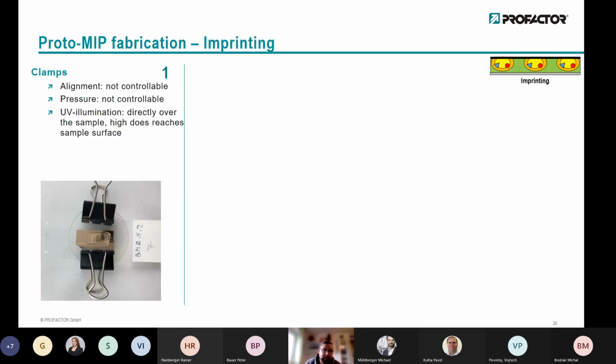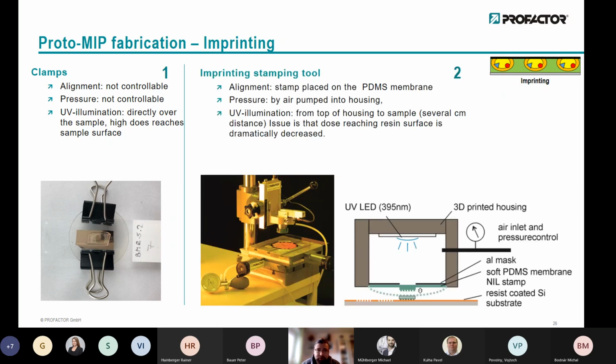So quite a challenge. Our first approach was quite naturally just clamping the things together, but you don't have an alignment control, you don't have a pressure control. The UV illumination, since we are focusing on UV, curing is relatively quick and relatively straightforward because everything is transparent to UV that we used. So this was the benefit. However, as the alignment and pressure control is critical here, we used something we developed in-house, what we call a stamping tool, where you basically apply the stamp onto the dedicated surface via air pressure. So here we have better control as well, also with the UV light.